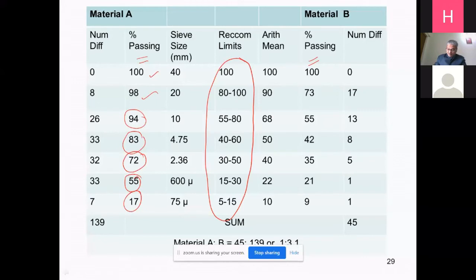For 40 mm it is okay, for 20 mm it is okay, but for 10 mm it is not fulfilling the criteria, for 4.75 not fulfilling, for 2.36 and so on. If you see the percent passing of material B, then it is not fulfilling the criteria for 20 mm. For others it is fulfilling, but for this it is not fulfilling.